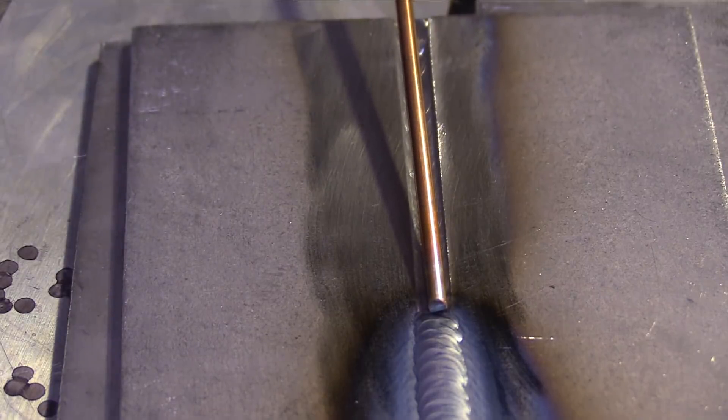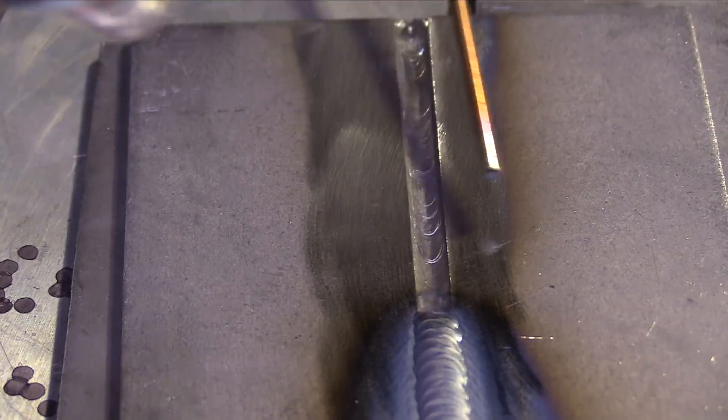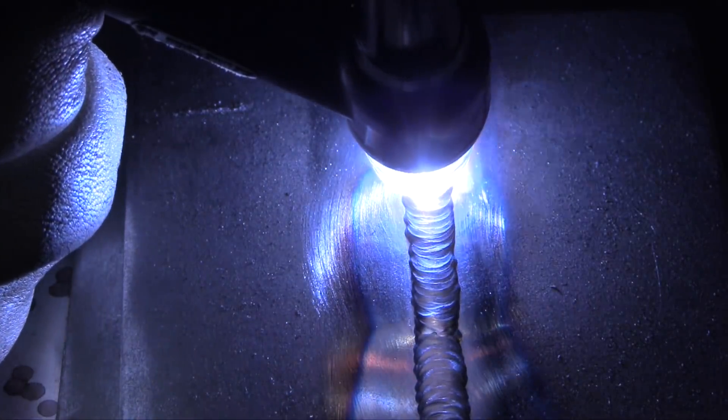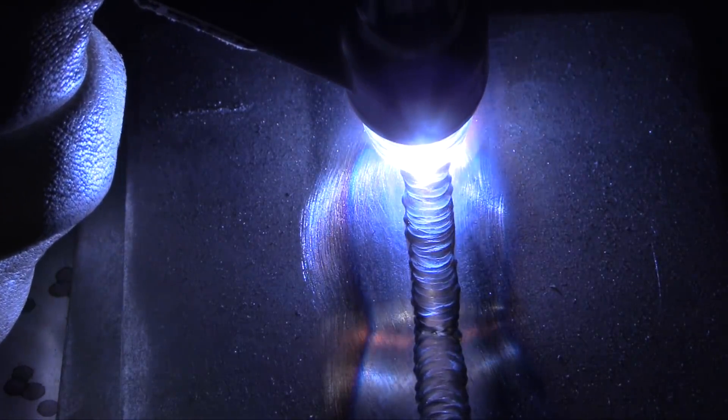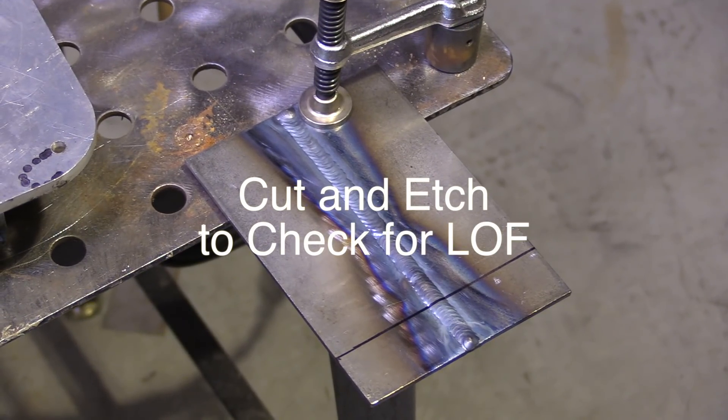Let's do the other portion now after letting it cool off for a little while. I always have to fight myself to let things cool and not get in too big a hurry. If you get things overheated, things don't flow the same, things get oxidized, you start pulling in some oxidation, maybe even melting through the back side if you don't let it cool a little while. I'm just doing sort of a Z weave right over that rod, keeping the rod in the puddle, just a little bit of pressure on the rod, not trying to feed any in there. Just trying to keep a little pressure on it so it stays in the puddle and doing a little Z weave, watching the toes, trying to make the toes look pretty good, not leave any cold toes. Toes are the edge of the weld, the very edge where it joins into the base metal.